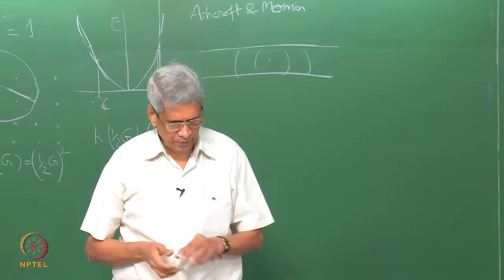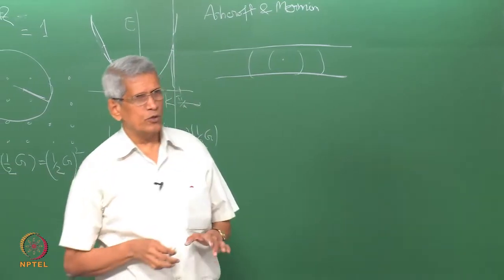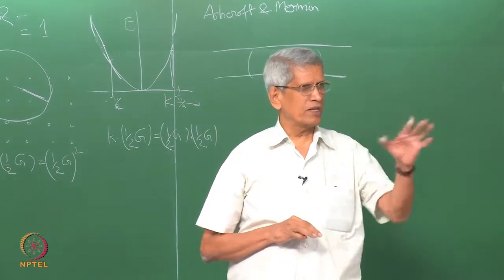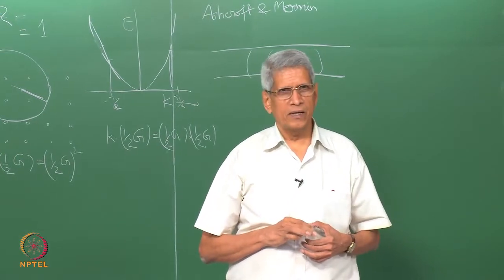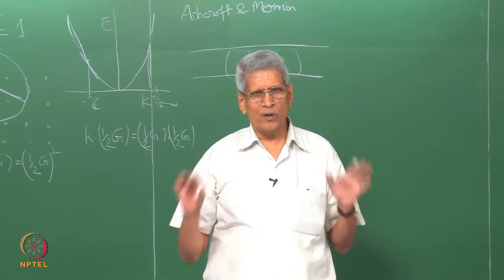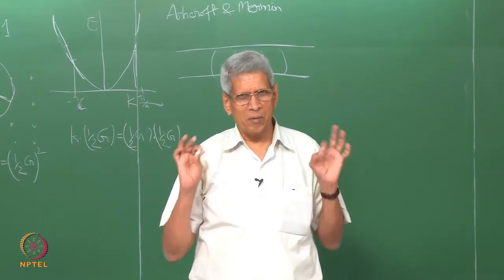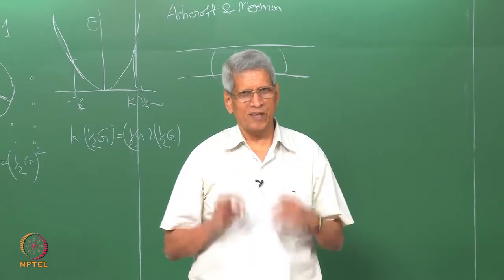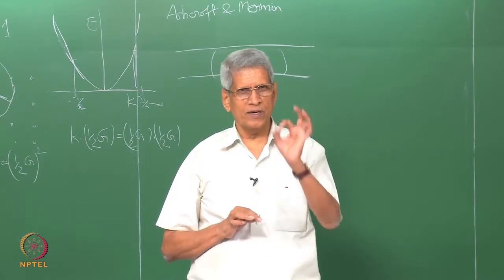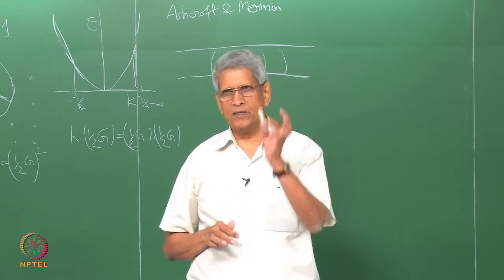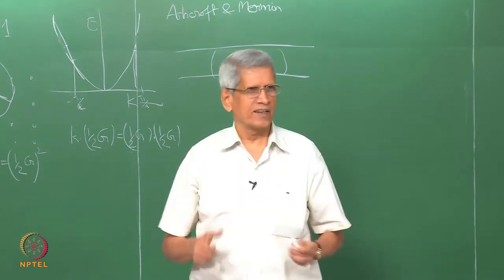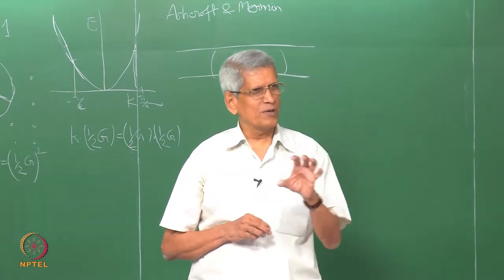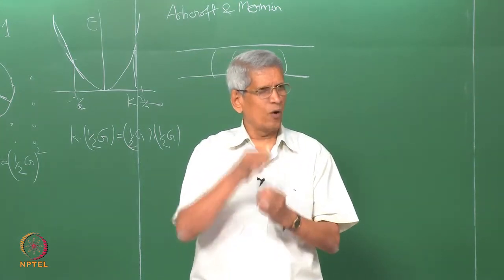Now, why I wanted you to know is that diffraction is a general technique. Suppose you are working with a single crystal, for example because you want to study the deformation behavior of a crystalline material, how it depends upon the orientation of the sample. Then you have to take a single crystal, and the loading direction has to be fixed in it. To do that, first you have to find out the loading axis of the crystal you have got.